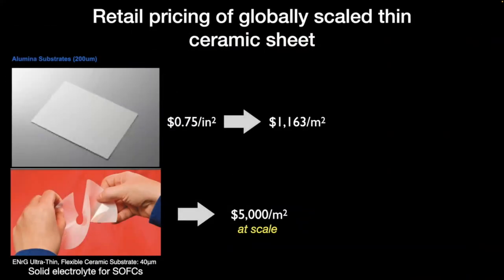We can look at that and you can just Google this. Not the bottom number, but the top number, just that from CoorsTek. What does it cost to get a 200 micron flat pinhole-free piece of alumina? About $1,000 a meter squared. And you want to be at a dollar. So that's actually three orders of magnitude too expensive.